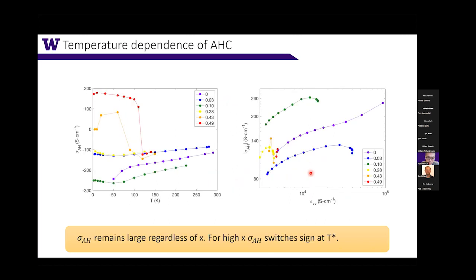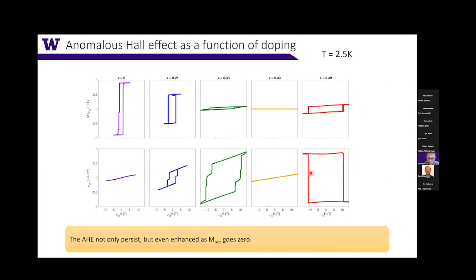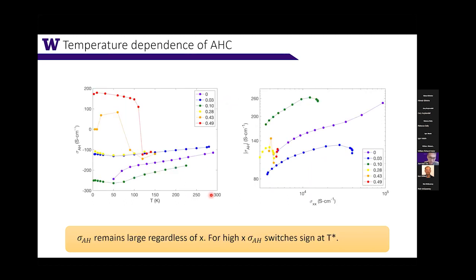Since anomalous Hall resistivity is not that transparent, or not that directly related to the things we care about, you can convert this to the anomalous Hall conductivity and plot it as a function of temperature. Then you see this reversal of the anomalous Hall conductivity as a function of temperature for certain dopings, but you also see that the magnitude of the anomalous Hall conductivity doesn't vanish and even gets stronger when you go to higher doping.